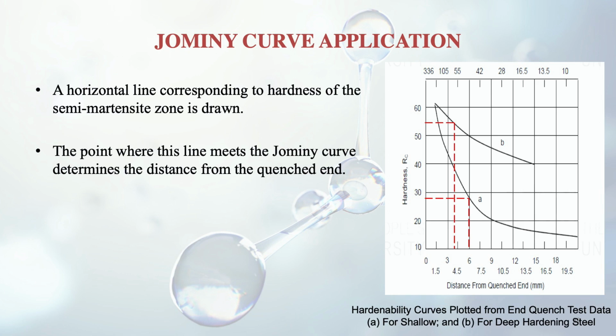And suppose you draw a horizontal line on the curve from the vertical axis, then that line will correspond to the hardness of the semi-martensite zone. Semi-martensite means that 50% martensite has been formed. That's why its name is semi-martensite. And then from the point where this line meets the Jominy curve, we draw a vertical line which falls onto the x-axis. From there we will get the distance from the quenched end for this hardness. So there are two curves here, one is A and the other one is B. The first one, A, is for shallow hardenability and the second one is for deep hardening steel. You can see and understand very well that it is deep hardening, because the hardness number is more in the case of the B graph.